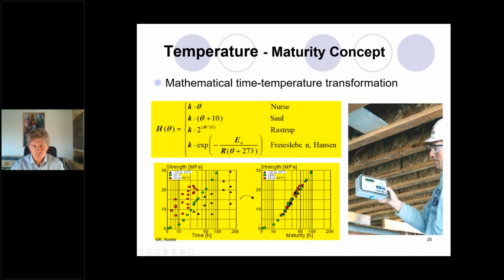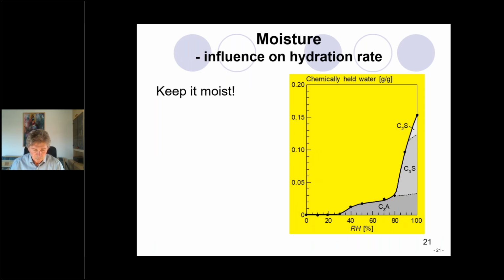It doesn't matter what kind of temperature was implemented during curing, all the points are lying on the same curve, which is very nice to predict, for example, when we need to demolish structures, when we can release the stresses from the reinforcement, from the cables, for example, if we are speaking about pre-stressed concrete. So there is a very, very important meaning of this maturity curve. And many companies produce this kind of instrument indicating the maturity immediately. I don't want to make any advertisement for any company.